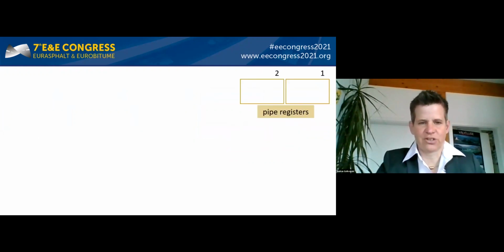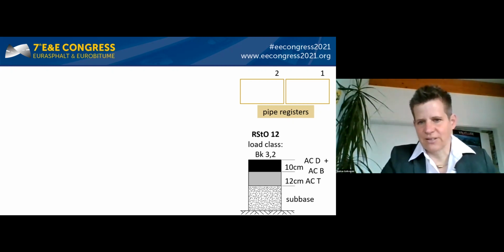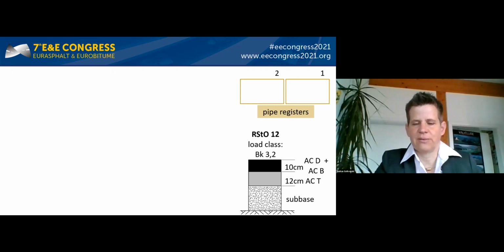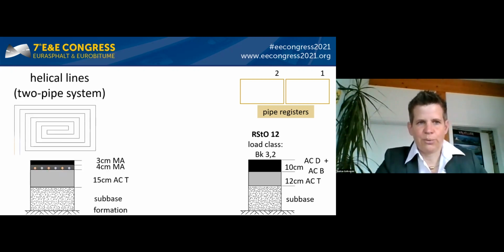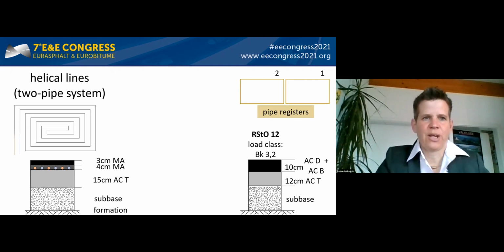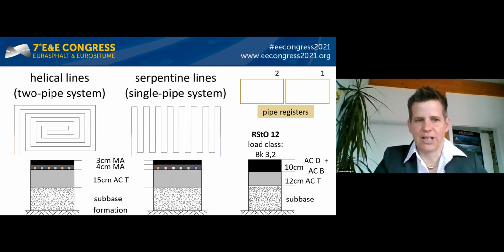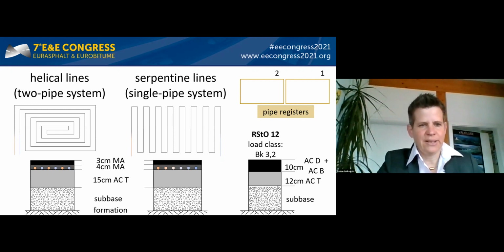So the two pipe register sections. All our test sections are referenced to a standard, the German standard RStO. We choose a loading class of BK 3.2, which means the upper structure is meant to last for 3.2 million 10-ton axle overruns within the lifetime of 30 years. We will have a two-pipe system with helical lines, and we also will have a single-pipe system with serpentine lines. The pipe registers are embedded into a 4 centimeter mastic asphalt course, and they will be covered by a 3 centimeter mastic asphalt wearing course.